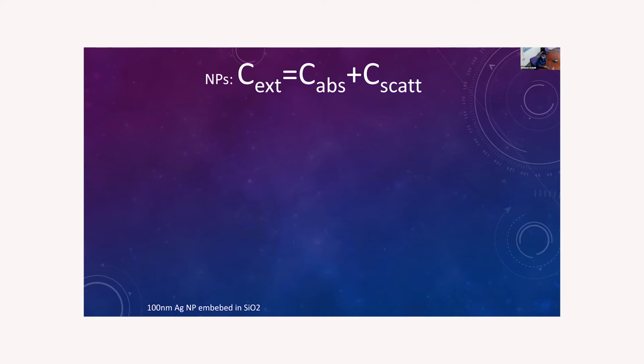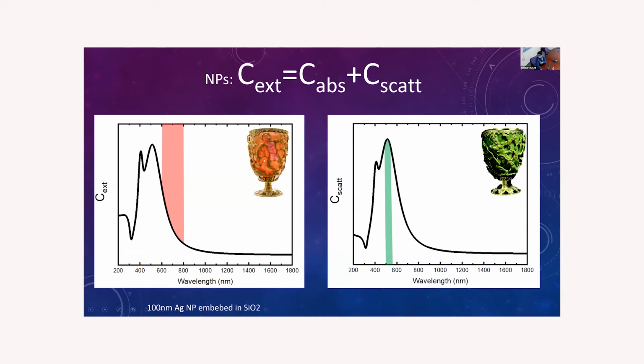So let's go to the first case that I will try to explain, that is the case of the Lycurgus cap. The Lycurgus cap, when it's lit from inside the cap, you can see the red color. If the light comes from outside, you see the green color. This is related to the extinction coefficient and the scattering coefficient. In this case, I have calculated the spectra of silver nanoparticles of 100 nanometers that are inside a silica matrix.